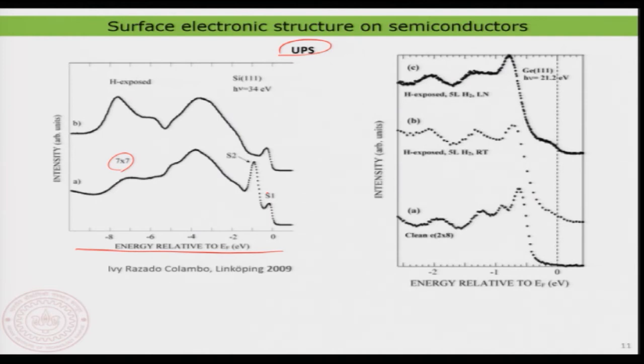But now, what I want to show you is what happens if I do a hydrogen exposure. You prepare the silicon 111 surface, which of course is 7x7 reconstructed, and then you deposit hydrogen on top of the silicon 111 surface, and you find something interesting. That is also why I want to show you this example, because you can see what is going on at the surface. Suddenly you see that the S2 peak is missing now. That is quite interesting.